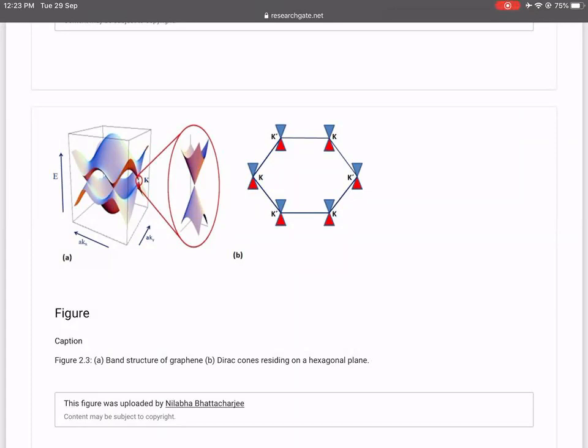All right, so this band structure is just a simple consequence of the fact that electrons are experiencing a periodic potential. There's nothing more to it. It's just the periodic potential that ensures that you have these bands. But that already allows us to understand why some materials are metals, they conduct electricity, while some others do not, and so on. So there could be a class of materials where, let's say, a certain number of bands are completely filled and the rest are completely empty, depending on how many electrons you have in the system. Those situations where the filled bands are separated from the empty bands by regions in energy where there are no electronic states are semiconductors or insulators.